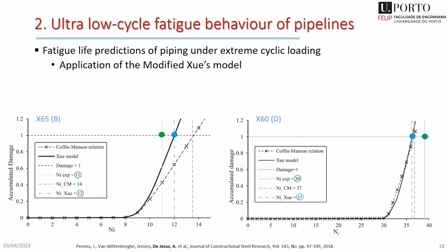We did that for two materials, two pipeline steels, X60 and X65, with different dimensions. And it was possible to get very accurate predictions. An error of one cycle in 12 or two cycles in 39. We have published a book about this. So if you want raw data or more information about the project, I can give you details later.